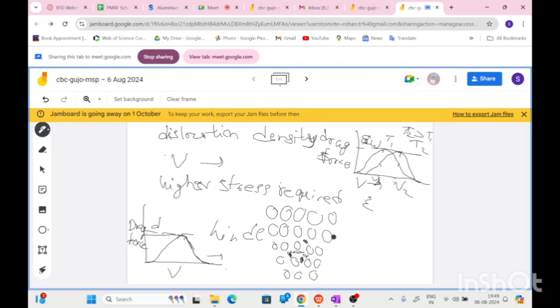Similarly, the strain rate is rho V b. Rho is the dislocation density, V is the velocity, and b is the Burgers vector. So strain rate is directly proportional to velocity. So if we plot the graph of drag force with strain rate, we get a similar curve. It means with increasing strain rate, the drag force first increases, then decreases, because the dislocation gets free after some point with an increase in drag force. Okay, so next I will explain in the next class.